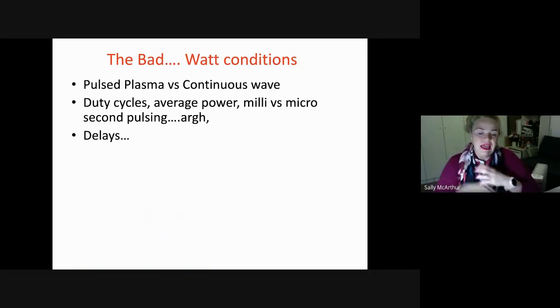So one of the interesting questions that we have with plasma polymerization is that our goal is retaining specific chemical features that are found in the monomer and translating that into the thin film that we form. And you'll note that I'm being really careful about calling it a polymer. It's a polymer network. It doesn't form your traditional polymer structures. You get more of a complex network of fragmentation and reorganization driven by different interactions with reactive species in the glow.